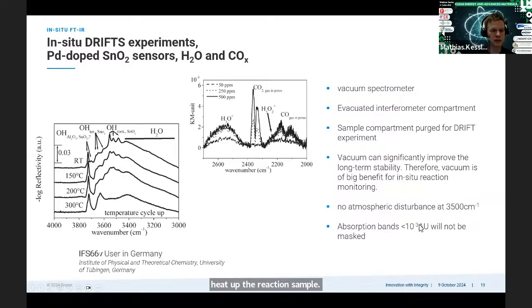We can use DRIFTS spectroscopy also for gas sensors. In that case, we can use, for example, tin oxide, which is doped with palladium. And we can use such reaction cells then to investigate the water or carbon oxide content on top of the powder sample. And in the spectrum here, you see again, if we go up with the temperature, how the adsorbed water is then removed from the sample. And in addition, we can see if we let gas flow over the sample, how carbon oxides, carbon monoxide or carbon dioxide is attached to the sample in the pores of this powder material.